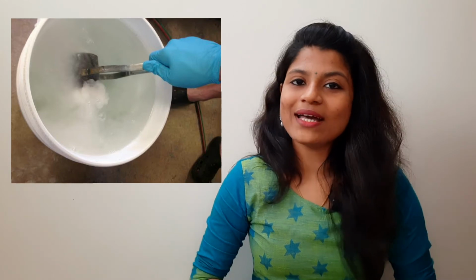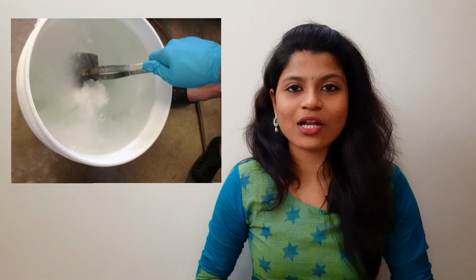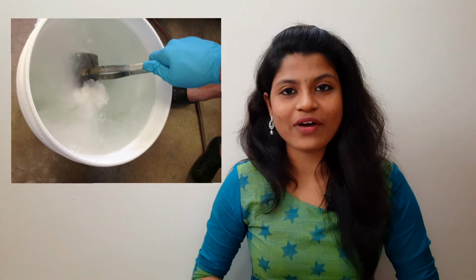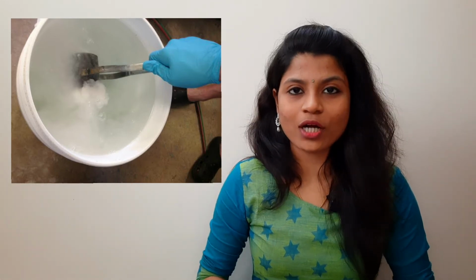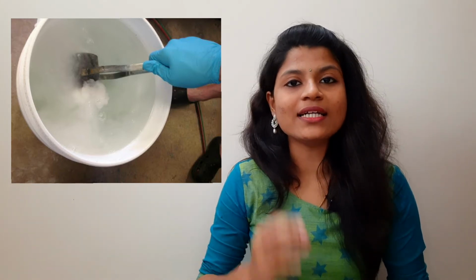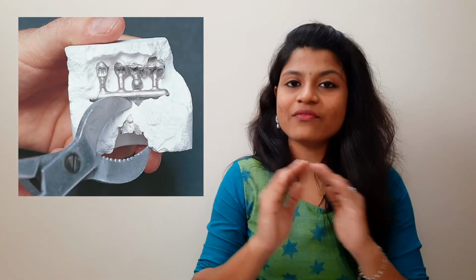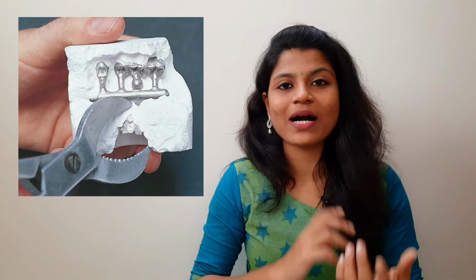Finishing and polishing is done by four processes: quenching, divesting, pickling and sandblasting. Quenching is done when the type 3 and type 4 gold alloy has been cast and solidified. The ring should be quenched in water once the bottom shows a dull red glow. Divesting is nothing but removing the investment surrounding the casting, or recovery of the casting which is surrounded by the investment. Once the casting is recovered from the investment, it appears dark due to oxides and tarnish.